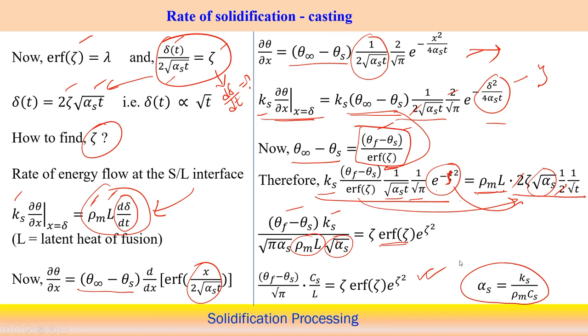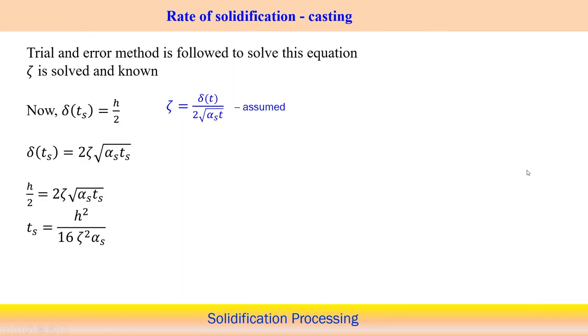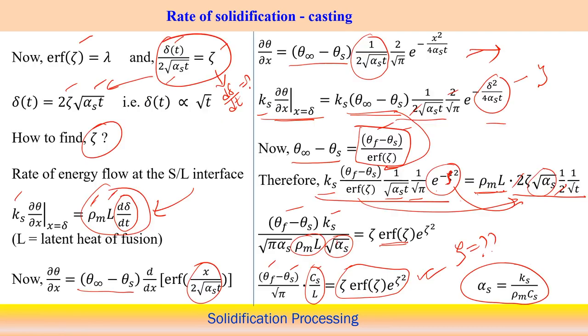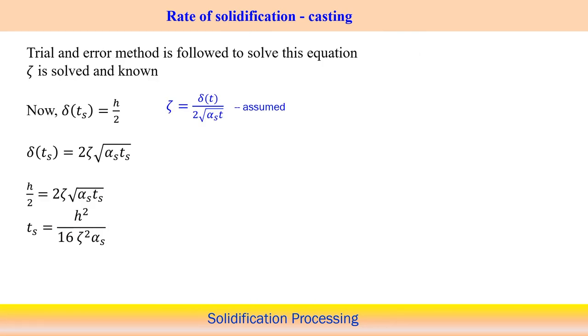Now here you can see it is theta f minus theta s; in this case theta s might be the unknown part, but theta f is the freezing temperature, which is well defined for a particular material, and C s is a material property in this case. But we do not know this value, so basically zeta is unknown here. Now zeta can be calculated from this equation, and we need to follow some kind of trial and error method to solve this particular equation.